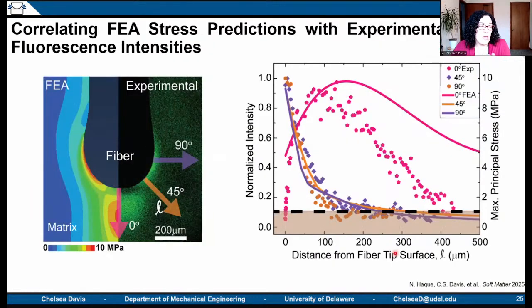And because we have the ability to see small features, we can start to do a little bit more thorough analysis in order to understand how good of a job our calibration is doing at describing what we expect to see based on what the finite element calculations of the stresses in our matrix are. So here I'll show that at 45 and 90 degrees, Nazmul got really great agreement between his experimental intensity as a function of position. You can think of this as how much stress is occurring in the system relative to the location or the shape of his system.